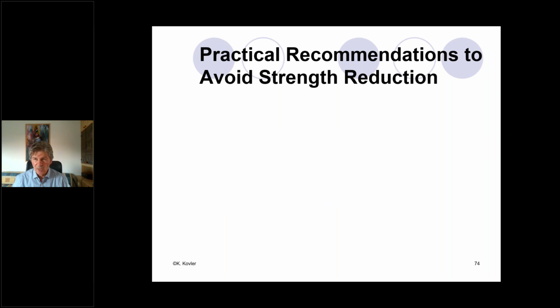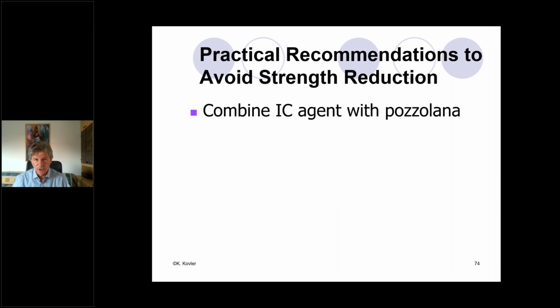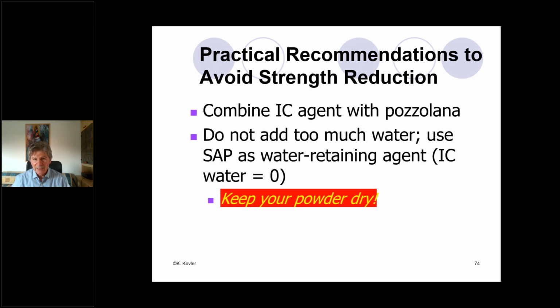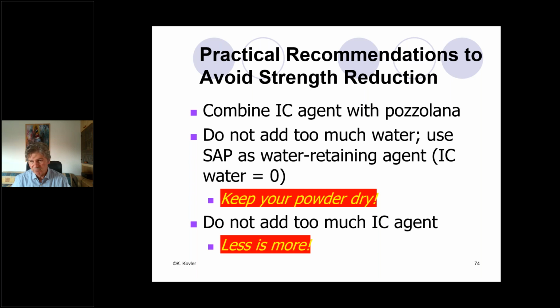Practical recommendations. I am coming to the conclusions to avoid strength reduction. First of all, as we recommended in some of our papers, let's combine this internal curing agent with some pozzolanic materials. Do not add too much water. Use superabsorbent polymer as water retaining agent and keep your powder dry. This is extremely important for an internal curing agent such as superabsorbent polymer. And do not add too much of this agent, not only from cost considerations, but also from the requirement of minimizing the strength loss.